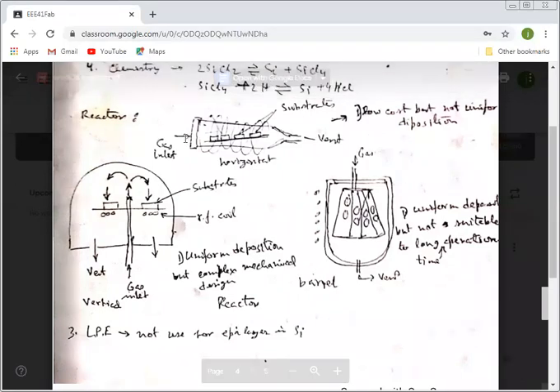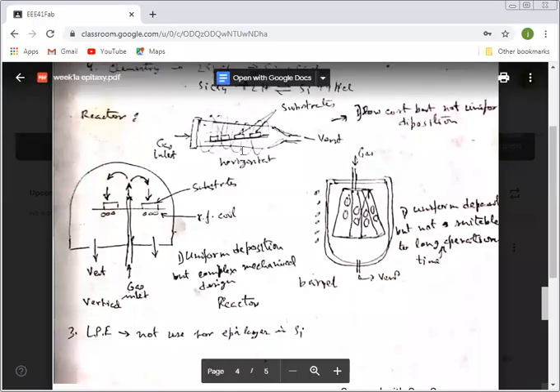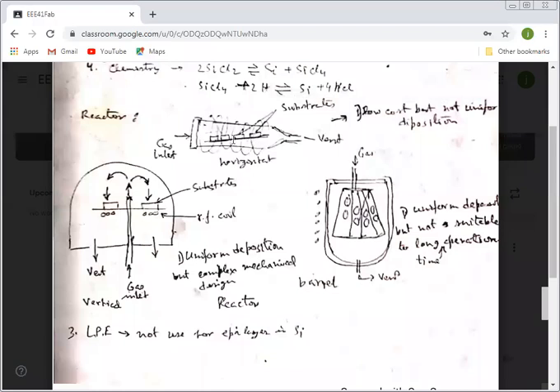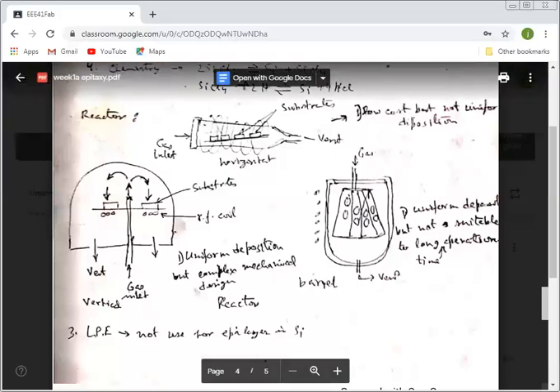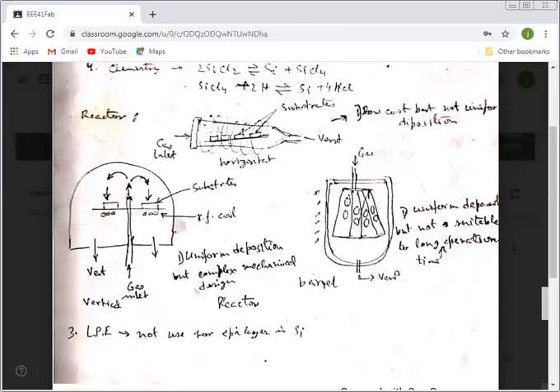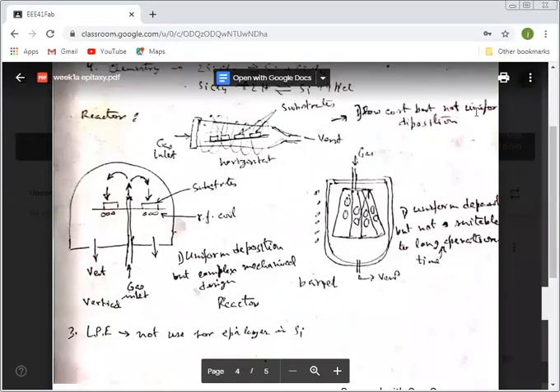And then from the left side, we send the gas chemical source. Around it is a heating coil, and we need a particular heating temperature, and then this gas goes through the wafer and gets out from the vent. So when it touches the wafer, it creates the epilayer of silicon. In this, we get low cost, but not uniform deposition. Since it is tilted, the deposition is not done vertically. It is kind of a tilted condition. So that's why the epilayer is not uniform.